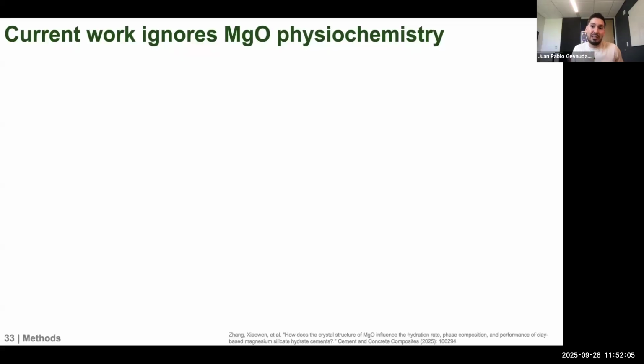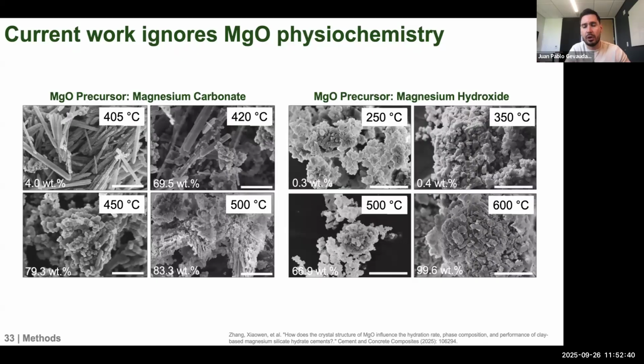So the first thing is just framing the problem. Right now, the magnesium oxide that a lot of work is using is lightly burned magnesia that is produced commercially, or magnesia that is produced in lab conditions through the calcination of brucite or magnesium carbonate. What we found is that the production of that magnesia, specifically in lab conditions, varies in terms of the temperature of calcination. So we started to look at two different precursors for magnesia, magnesium carbonate and magnesium hydroxide, and at different calcination temperatures that we would see in the literature.